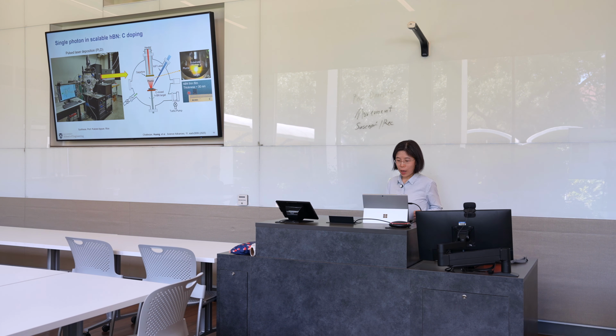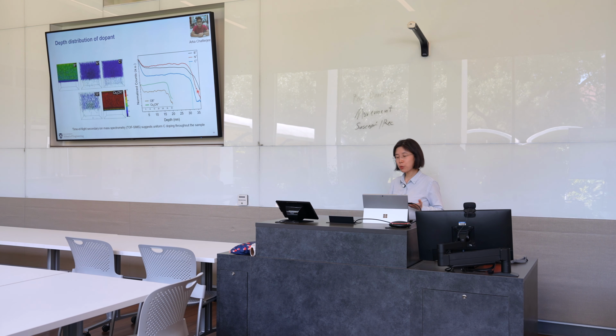And as a result, we have a thin film of boron nitride with a thickness of about 30 nanometers. And in this boron nitride thin film, we have carbon defects. So first, we want to understand the depth distribution of the carbon dopant. So we use a technique called TOF-SIMS, time-of-flight secondary ion mass spectrometry. So you can see the carbon distribution on the depth profile looks like this. They're relatively uniformly distributed across the entire depth of the sample.